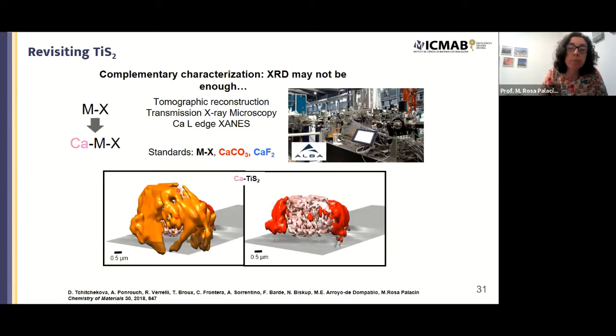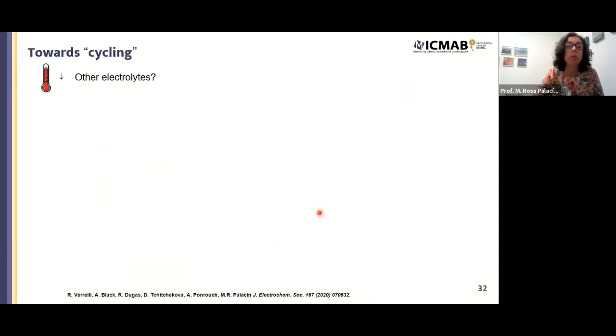So these are the particles, and the calcium density here could correspond to some sort of calcium carbonate. Then this density of calcium here underneath would be in agreement with calcium carbonate. And finally, these pink bubbles correspond to calcium ions inside the TiS2 particles. So we really confirm that calcium is inside the structure and this is reversible. So as I was mentioning, this was not a very practical result, and we were looking at the influence of the electrolyte and the influence of temperature, because it is not really practical to operate at 100 degrees C.